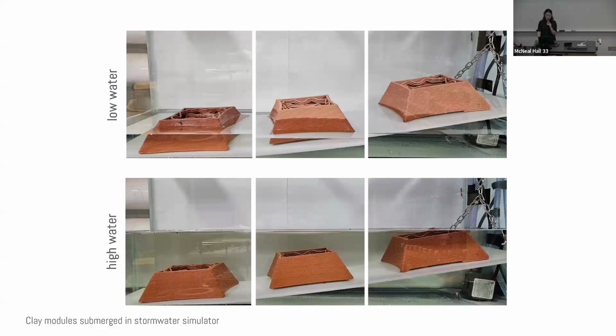So this is the apparatus we set up at SAFL, St. Anthony Falls Laboratory. In our laboratory experiment, we are aiming to understand the role of varying water levels on the modules and material integrity. So the test simply replicates how a stormwater pond functions. They fill rapidly during stormwater events, as real stormwater does. And then they slowly release water to downstream water over a period of 48 hours. And that's exactly how a stormwater pond behaves.